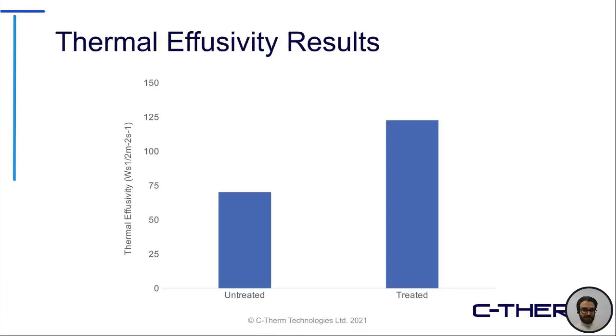And again, as a singular example here, some of the materials that were tested, both treated and untreated, you can see quite a significant difference in the overall thermal effusivity measurement. So it's the same fabric with simply a different coating, or one with and without a coating, and you can see how that affects the overall thermal performance of that sample.